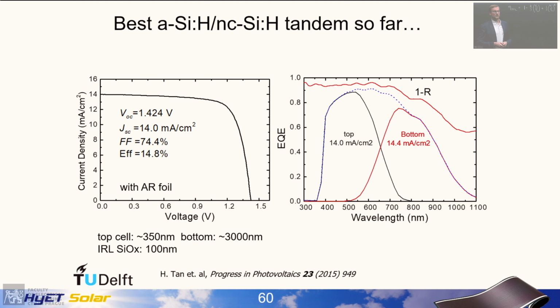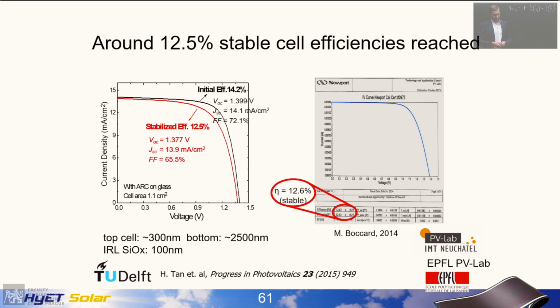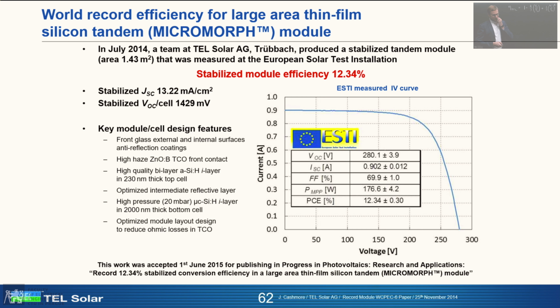And indeed, it was demonstrated a little while later that tandem devices could be made, and this is still the record from Delft, 14.8% for a tandem cell. And then for stable efficiencies, because that's also a thing, amorphous silicon degrades when exposed to light, we reached with the community about 12.5%. This is a result from Neuchâtel that you see here. And also, a very large scale is possible. So this was the last result of Tokyo Electron. They made a module, and the efficiencies reached 12.3%.